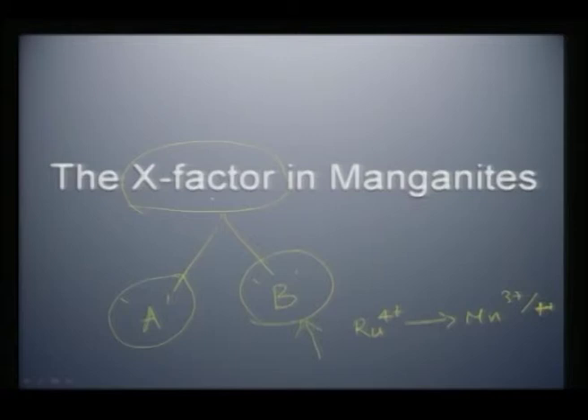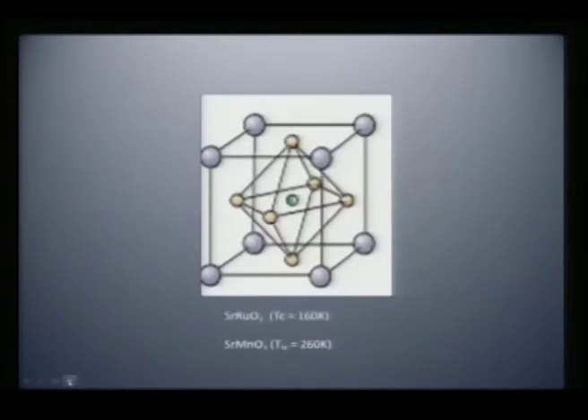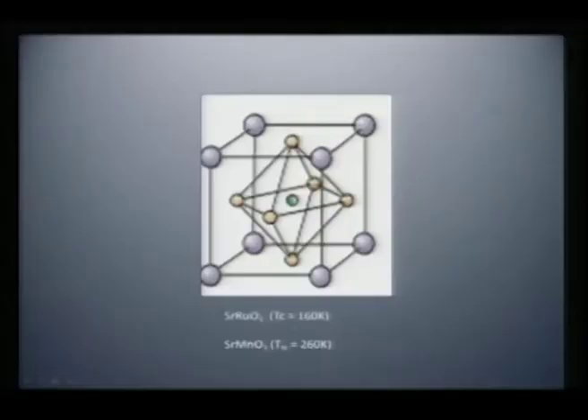So, what would happen if you substitute in equal proportions? I take a case study of strontium ruthenate and strontium manganate because this is more of a reverse doping effect. This is a known ferromagnetic metal, one of the very popular ferromagnetic metals in the ruthenate series, among ruthenium oxides. On the contrary, if you take SrMnO3, it does not show a ferromagnetic metallic state, it rather shows an antiferromagnetic insulator state.